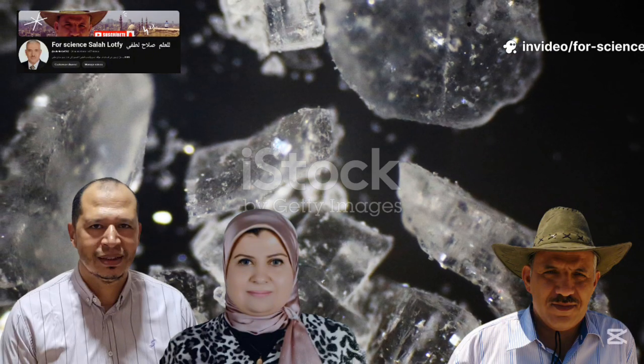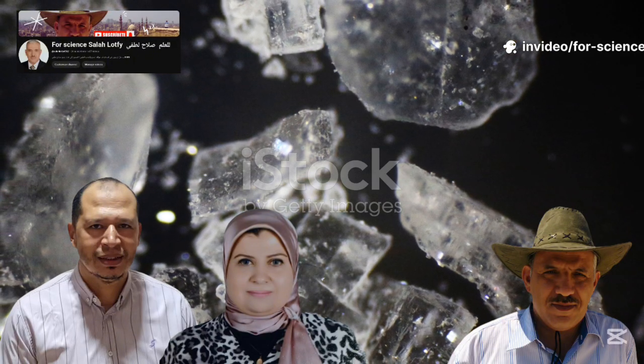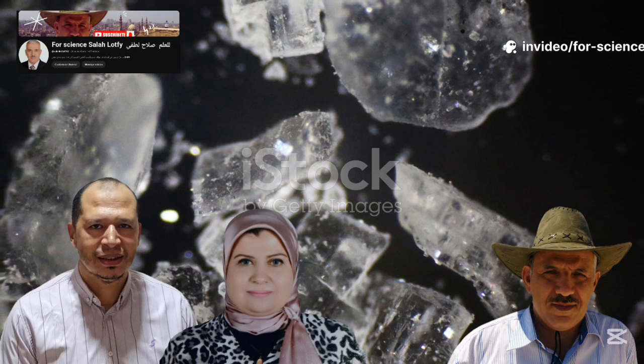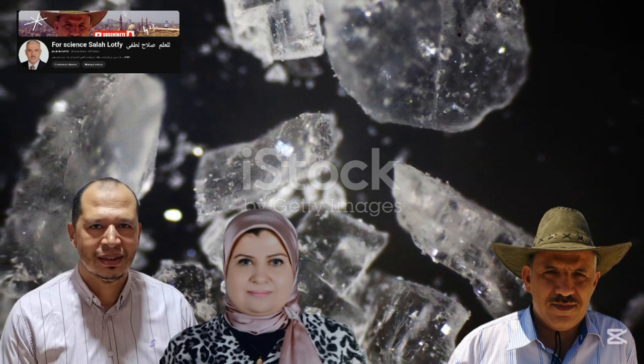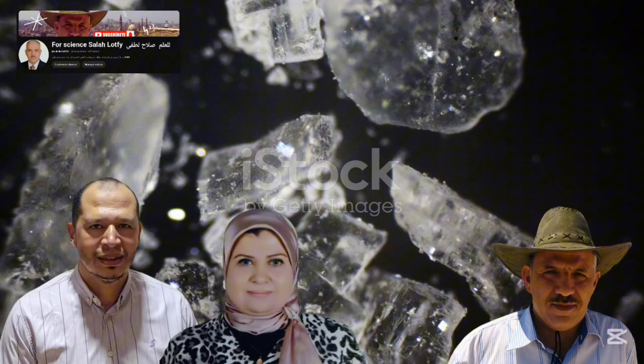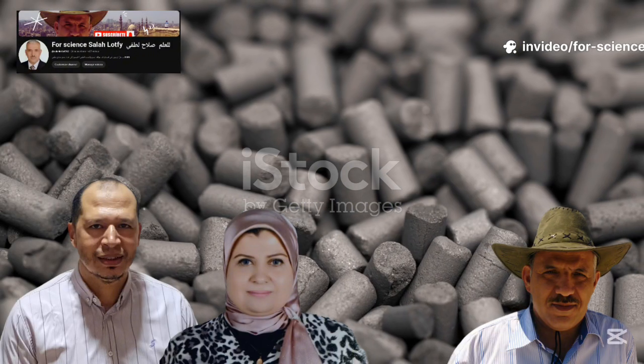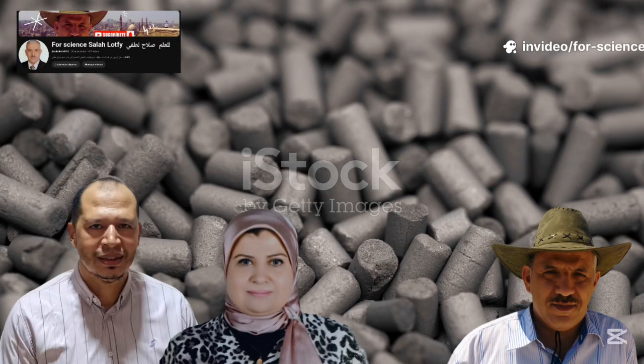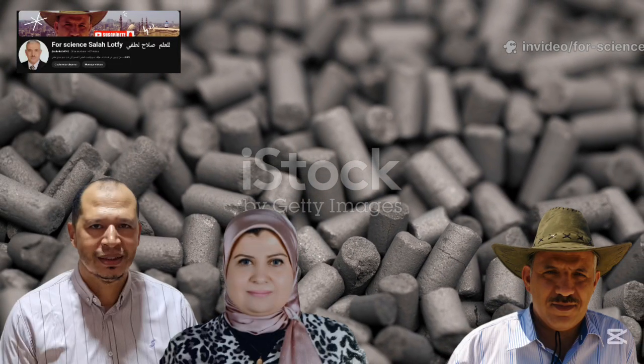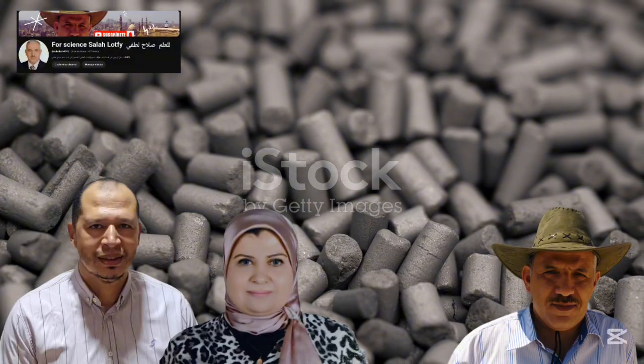To enhance the sensor's performance, the hydrogel was loaded with calcium chloride, CaCl2, and charcoal. Calcium chloride acts as a hygroscopic agent. It strongly attracts and holds water molecules from the surrounding air. Charcoal contributes its porous structure and large surface area, increasing the hydrogel's ability to absorb humidity and improving its mechanical stability. Together, these fillers create a composite material that can absorb more than 11 times its own weight in water vapor and reach a swelling capacity of over 240 times its dry weight in water.